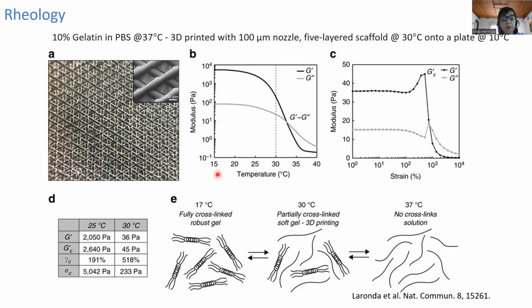And we have here the modulus. It depends on temperature. As you see here, this is G prime. As you remember, this is the elastic part of the material, the elastic behavior. And this G double prime is the liquid or the dissipative part of the material. At low temperatures, the behavior is more elastic than like a liquid. But at higher temperatures, above 30 degrees centigrade, the behavior changes. It's more liquid than a solid. So here, you have at this point the transition from liquid at higher temperatures to solid at lower temperatures. This is what is called the transition sol-gel or the gelation temperature.